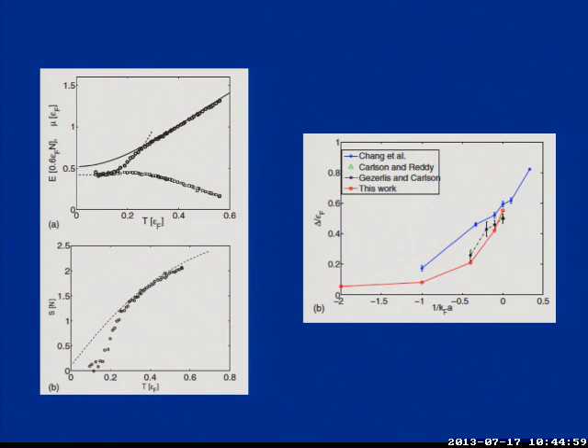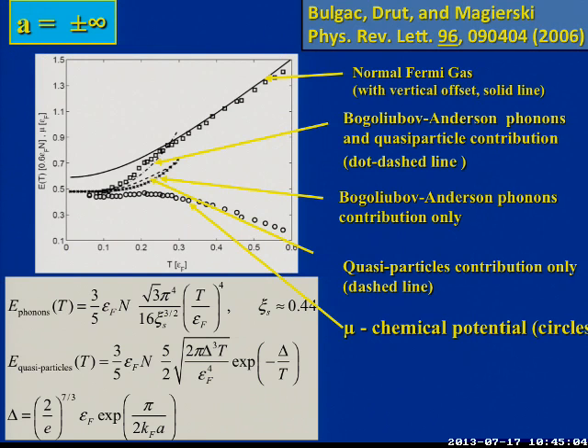Aurel? Yep. With respect to the previous figure. This one? Yeah. So when you have a lot of quasi-particles in the background, the phonons will be very strongly damped. So essentially, these phonons will decay quickly. I'm not claiming this is a theory. I simply took non-interacting broken pairs and non-interacting phonons and put them together. If there is an interaction, there is some. Maybe that accounts for the slight disagreement, but I didn't worry about it. And this is true only when the temperature is significantly lower than delta. So this is not completely correct.